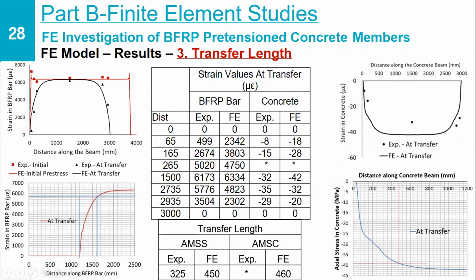So the transfer length obtained from the experimental study is 325, and this is from the strain gauges. So it is 450 millimeters from the finite element investigation. However, as I said, there was debonding of the strain gauges on the concrete, so we could not get the experimental transfer length, but the finite element showed a transfer length of 460 millimeters, which matches quite well with the transfer length that has been obtained with the strain gauges on the steel, on the BFRP bars.